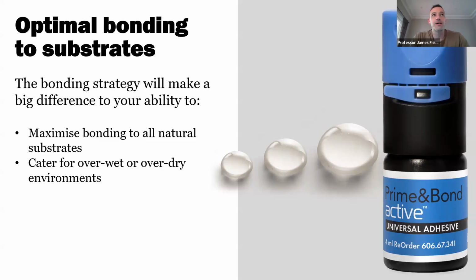One of the things which, as academics, being a bit boring here, I often used to talk about was, when we're preparing cavities for restoring and we're getting our materials ready to bond to dentine, how do we know how moist the dentine surface is? We've just washed and dried the cavity, but what's the end point of drying? How do we know where the optimal amount of hydration is? Because we know that over-dried dentine collapses and that over-wet dentine will compromise significantly the bond with the hydrophobic resin that we're trying to create.